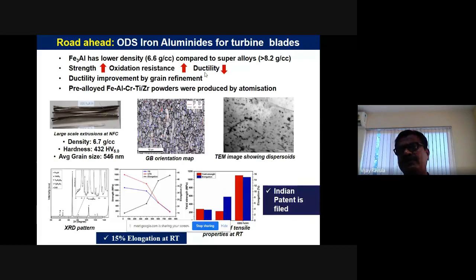But you know that when you go into nanostructured materials, the finer the grains, the higher the ductility of the material, and that's what we have employed. And how do we retain the finer grain size? By dispersing fine oxides. So we have done that with the iron Fe3Al material, with oxide dispersed in this intermetallic, and we have extruded it and made the rods, and you could see that different oxide particles are present, and the strength levels are very high, and even the ductility is very high. We were able to achieve around 15% ductility at room temperature.